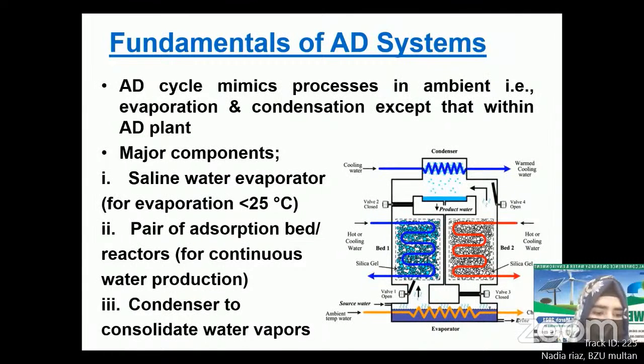In the evaporator, chilled refrigerant is circulated through tubes, while seawater is sprayed over external surfaces of tube bundles as shown in the figure. Initially, the evaporation occurs by a heat source that ranges from 2 to 25 degrees Celsius, but during the adsorption process, the evaporator pressure drops due to adsorption and contributes to the evaporation. The adsorption process ends when the adsorber bed reaches an equilibrium state.